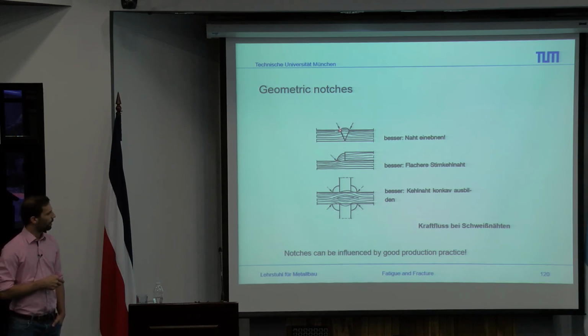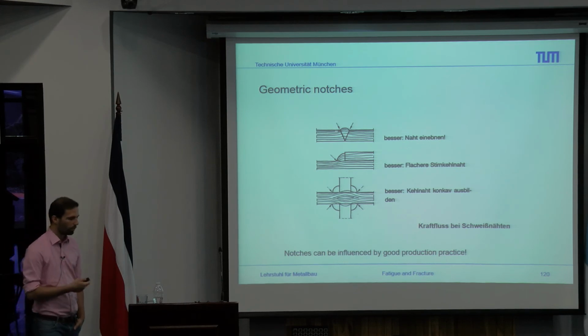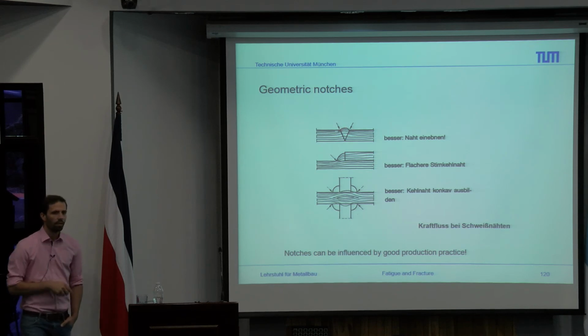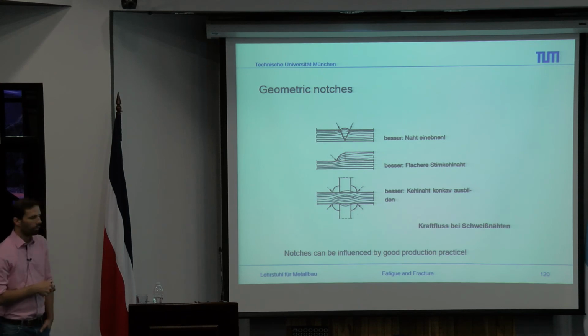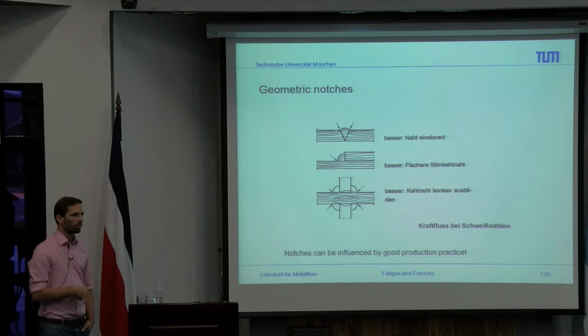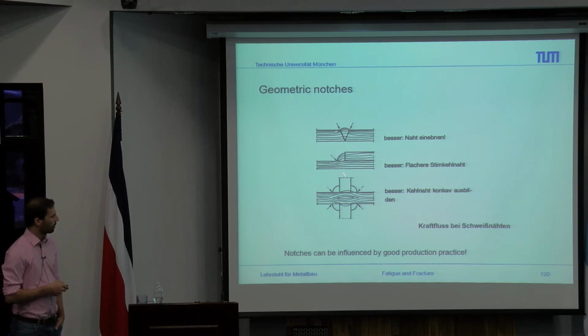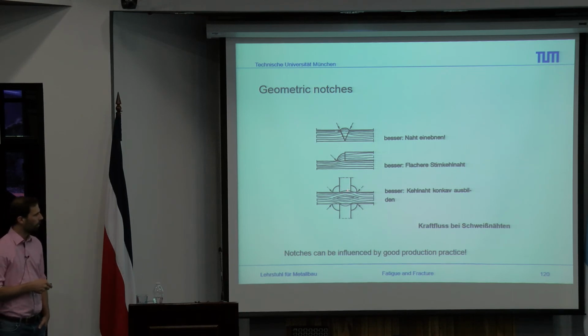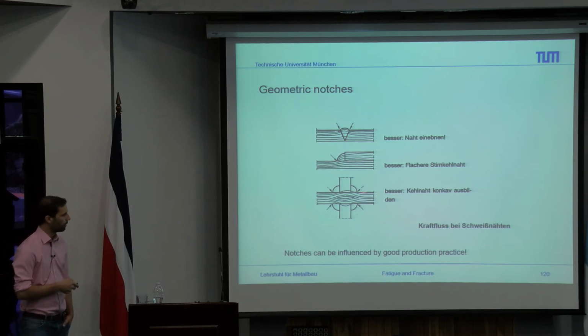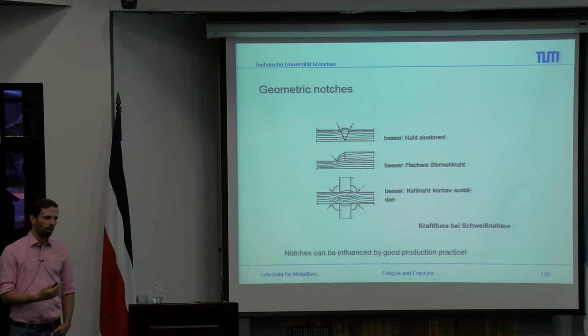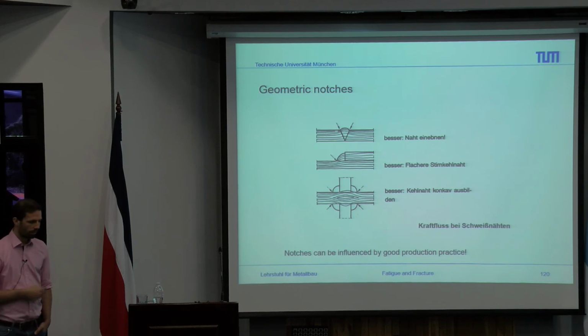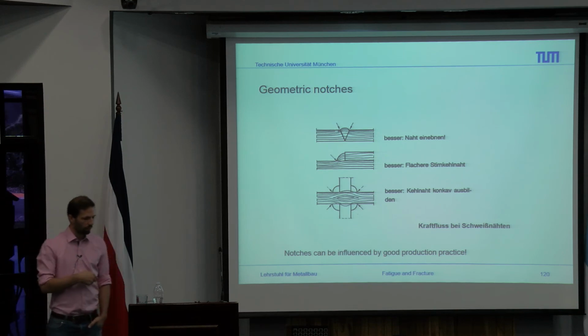So, for example, a better quality would also be to just take off the weld seam and make a flat bar. This could improve your quality and also give you a better resistance curve. And at this part, of course, you have a notch failure at the K shape of the weld seam. These notch failures can lead to crack initiation at this part here, but also the weld seam here is quite huge. If you have a smaller weld seam which can still handle the stress, then the stress increase due to the weld seam is smaller, and so the number of cycles which you can handle is increased.